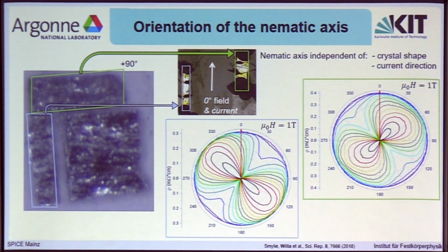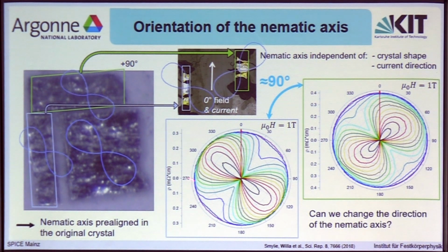And I just want to point out they're not only pointing along different directions, but if you look a little closer, they're actually related by almost exactly 90 degrees. So if I were to take this and put them here, you would realize that the maximum and the minimum Hc2, or the nematic direction, is actually already given in this large crystal piece that we had here. And cutting these two crystals from this large piece did not change anything to the nematic axis.